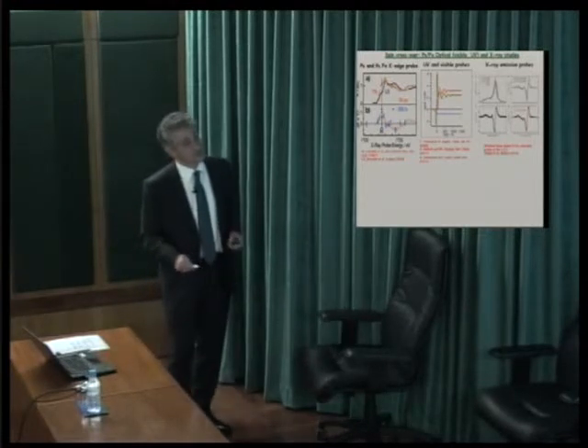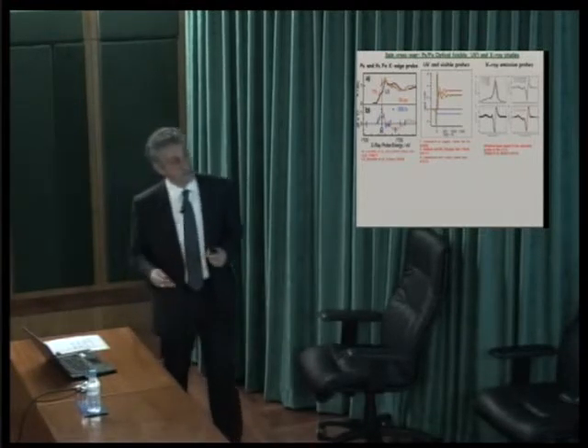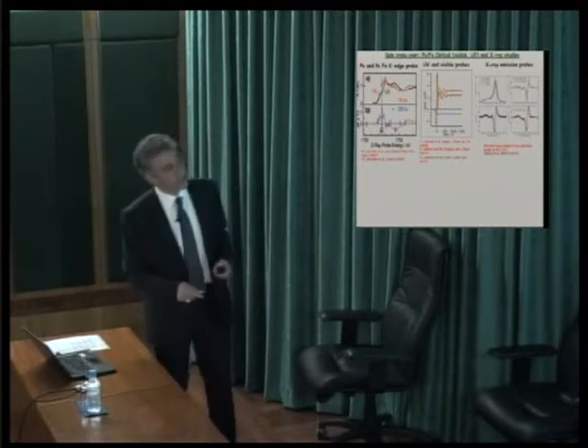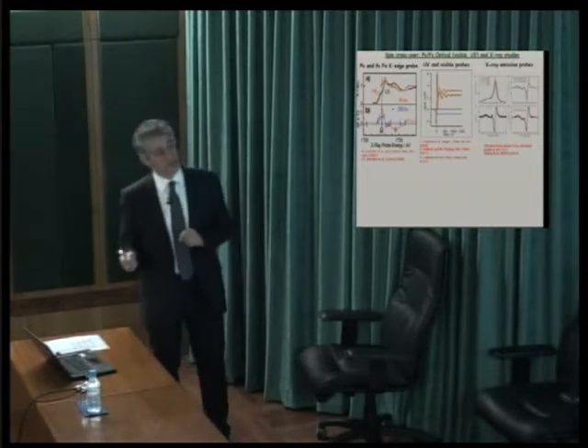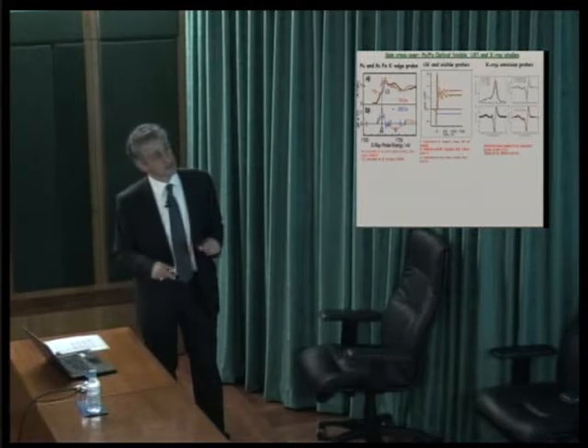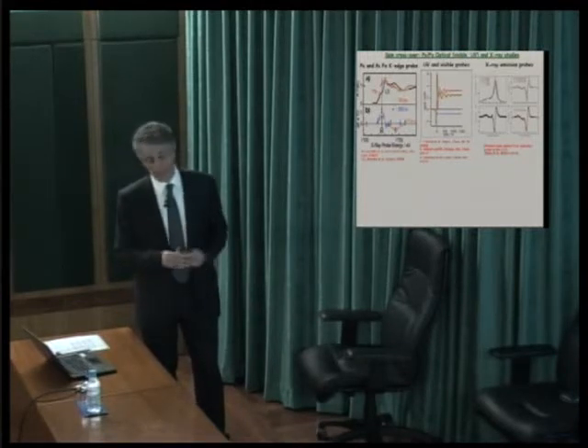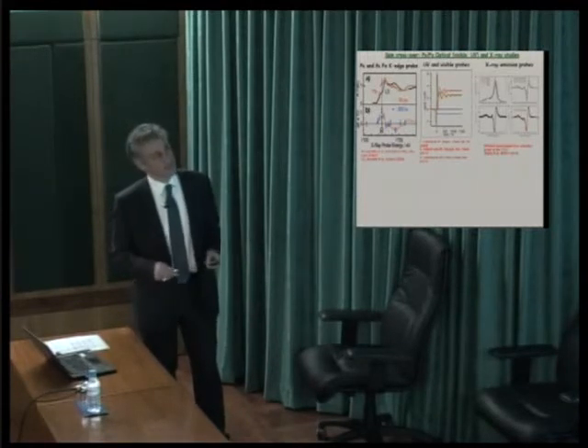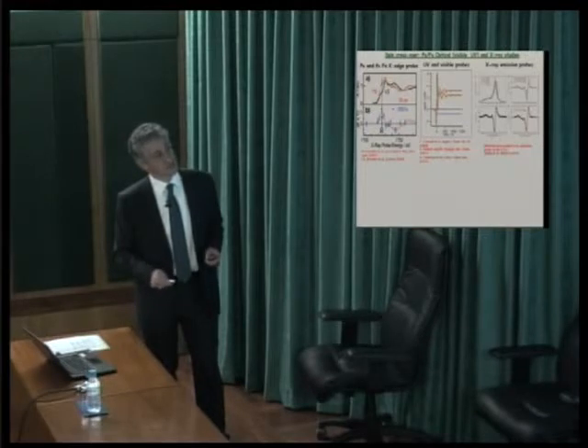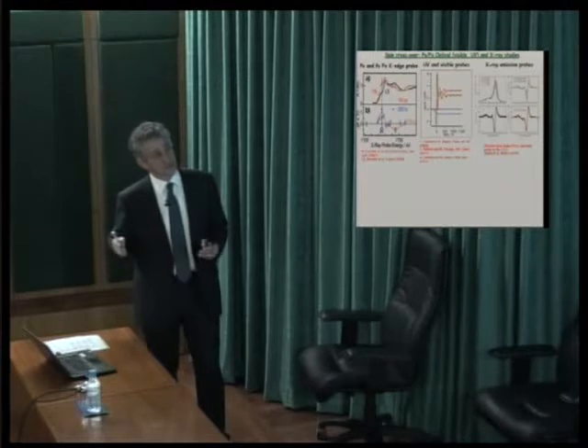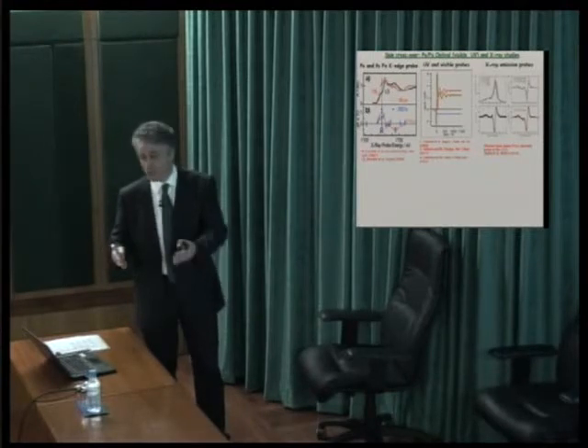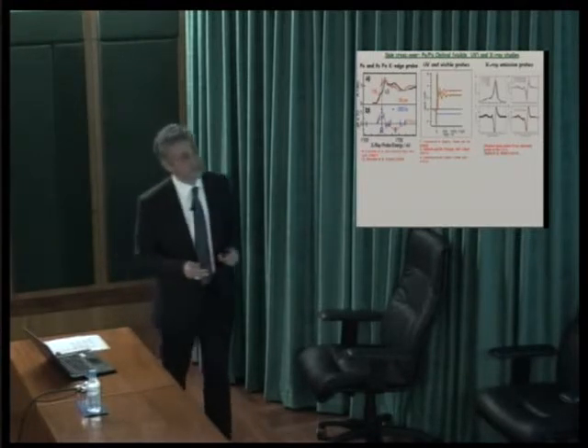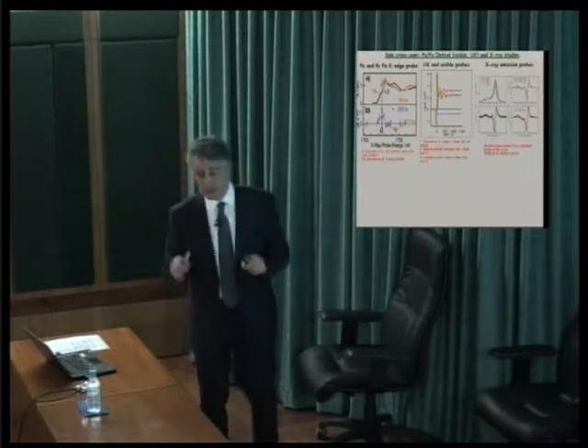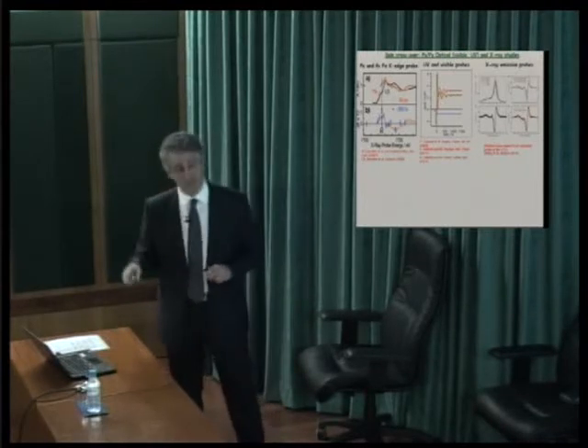And then we found observables also in the deep UV range, and we could show that the low spin to high spin state goes in about 50 femtoseconds, which is diabolically fast. And then the group of Kelly Gaffney implemented X-ray emission probes. So you excite the system with a laser pulse, and you probe with a pulse from the free electron laser, and you record the X-ray emission at each time delay.